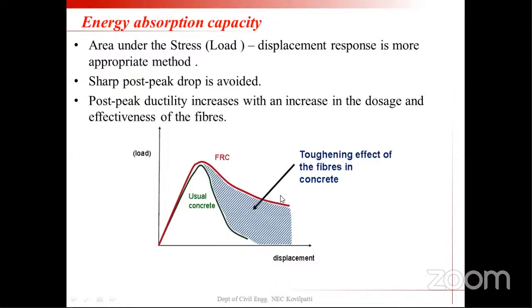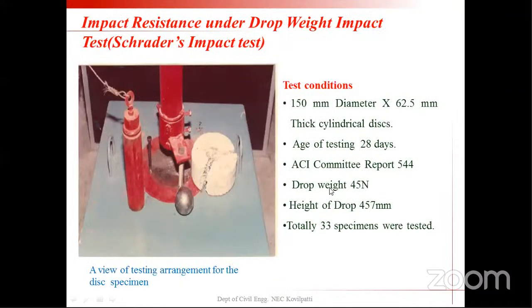So what is energy absorption capacity? This is the area below the load displacement curve, or the stress displacement curve, whichever is appropriate. If it is strain softening, we can take stress versus deflection. If it is strain hardening, we can take stress versus strain. Here the sharp post peak drop is avoided in the energy absorption capacity. You can see the long plateau after the post peak has been reached, and post peak ductility increases with the increase in dosage and effectiveness of the fibers. Normally, the area below this curve is taken as the toughening effect of fibers in concrete. And to measure the toughening effect, I have taken three mechanisms.